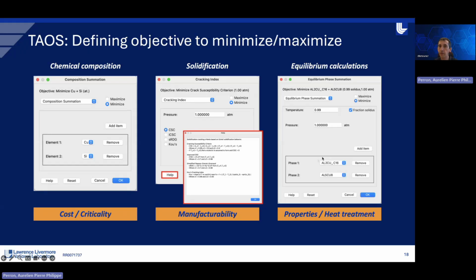So you can select the phases that you would like to form at a given temperature. Here, one interesting feature is that you might know your temperature, your surface temperature. So if you're interested in some precipitate at a given temperature, you can do that. So that's the absolute temperature. But if you don't really know that, you can always select the option of the fraction of solidus. So you can also use a relative temperature compared to the melting point of the